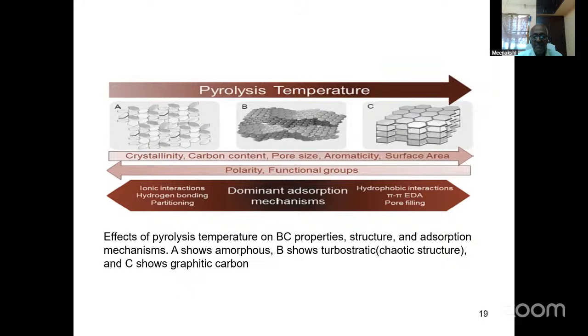When it increases, the crystallinity, carbon content, pore size, aromaticity or surface area increases. But at the lower temperature, the polarity and functional groups increase. So this is actually the effect of pyrolysis temperature on biochar properties, and how the structure and adsorption mechanism vary.